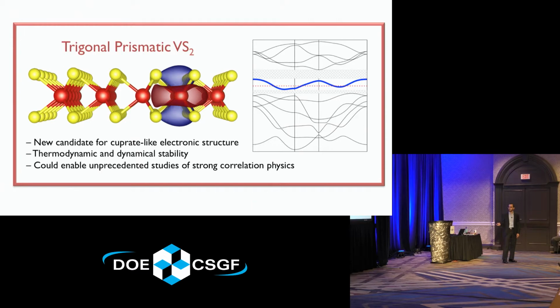We have significant evidence for the thermodynamic as well as the dynamic stability. And this, if synthesized, could really enable unprecedented studies of strong correlation physics and Mott insulating behavior. So we're very excited about this material. You can see here that we really came up with one particular material via some simple rules, kind of staring at the periodic table for a while, and we studied it in depth.